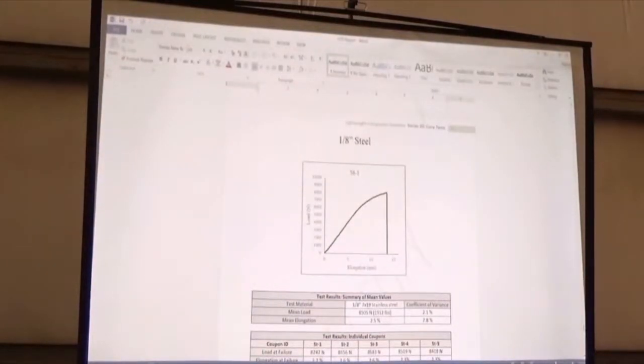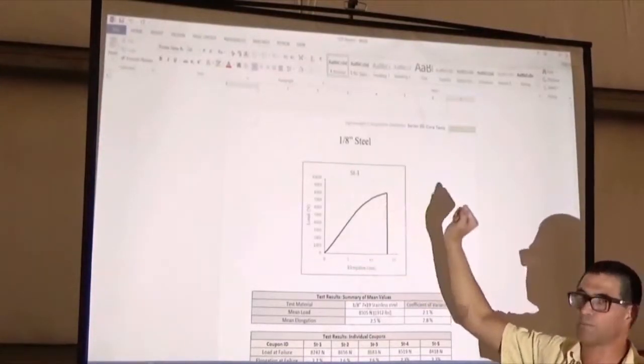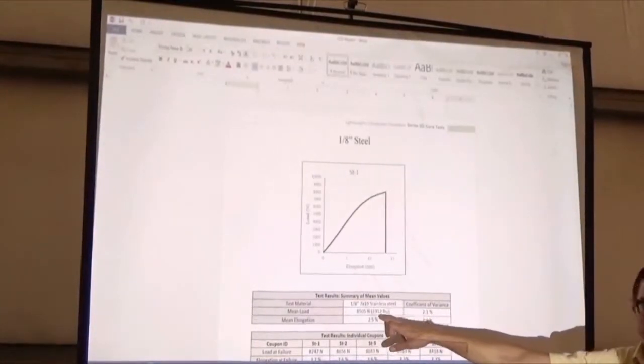And very quickly, I'm going to skip the last section of testing, which is testing of actual parts. But if you want to look, this is an engine mount bracket that you can look at later that got tested. This is a tail wheel bracket that got tested. And the last thing I'll talk about very quickly is those rudder cables that were going around. So this is steel, and again, very typical failure for what you would see for steel. You've got your linear region, and then you have it starting to fail here. And average load was about 1,900 pounds, and that's pretty much book. If you look in the Aircraft Spruce catalog, they'll tell you that 1/8-inch steel is rated for something like 1,950 pounds, I think.